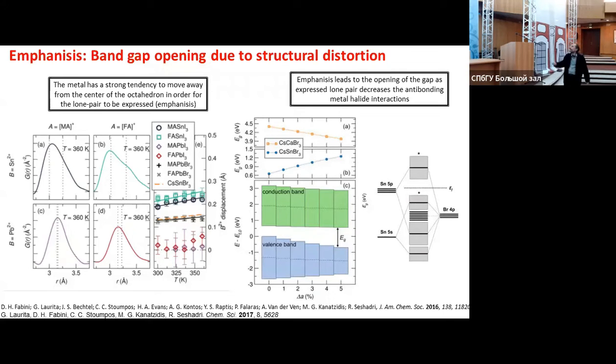And this is a phenomenon that Mercouri Kanatzidis, when he was working with lead chalcogenides, termed emphanisis, meaning appearance. There is a shoulder appearing here, a second distance in the proximity of the metal ion. This is the deformation of the octahedron. And its response all goes back simply to the nature of the orbitals on top of the valence band. This is what changes with temperature. And if I remember, in the beginning I told you that this has a contribution. These orbitals at the top of the valence band have contribution from the s orbitals of the metal. So the metal plays a role in the valence band. And this is what shifts up and down as you change the temperature, from delocalized to localized. And this also changes the dispersion on top of the valence band. And this is responsible for all these properties.